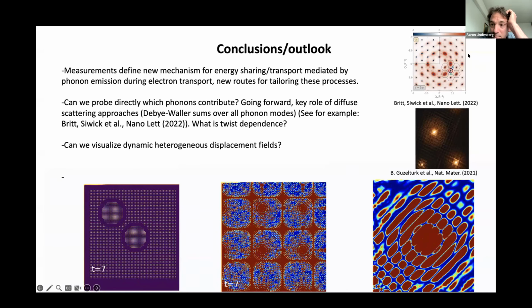I will mention there's already been some very important work, and this is experiments from Brad Siwick's group, for example, in monolayer MoS2, I believe, probing the buildup of the low energy acoustic modes. The black areas are Debye-Waller-like response, but you can see the Bragg peaks are broadening outward as well, giving rise to excitation into the low energy acoustic modes that are mediating the relaxation